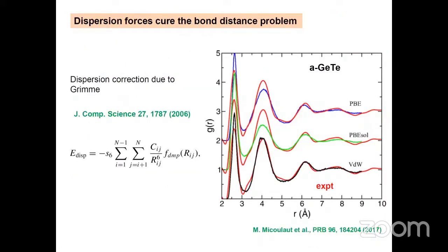And second, we realize that if you include dispersion forces, which is a correction due to Grimme, a dispersion force behaves as 1 over R to the 6, where R is the distance between the atoms or the ions. In this case, you correct the structural models that you obtain very nicely, and now they compare very well with experimental data.